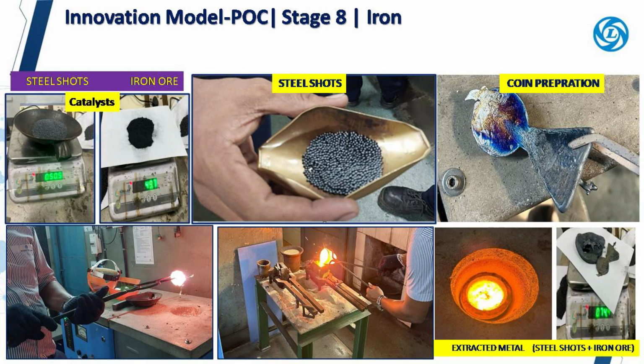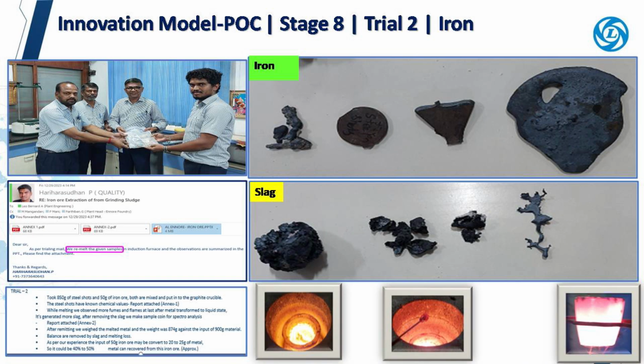We decided to add the steel shots in stage 8 POC concept and made trial 2 observations. Out of 900 gram of material, 874 gram was recovered with the remainder lost as slag and fumes. When 850 gram of steel shots were melted together with 50 gram of iron ore in the crucible, the 50 gram of iron ore yielded approximately 20 to 25 gram of metal. This indicates a metal recovery rate of about 40 to 50% from the iron ore.